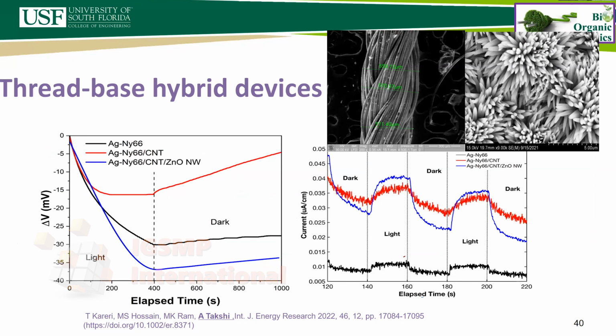We are in the process to start putting many of them together. By putting them in series, this 35 millivolts can be jumped to 70 millivolts, 100 millivolts, just by adding several fibers in series. Or we can put them in parallel to get much higher current out of the system.